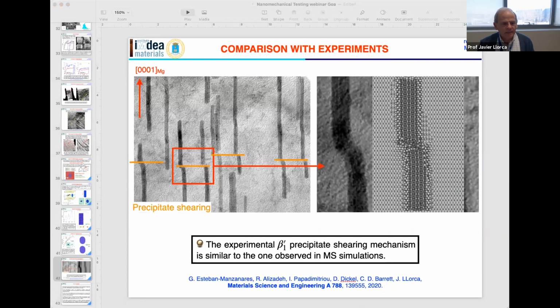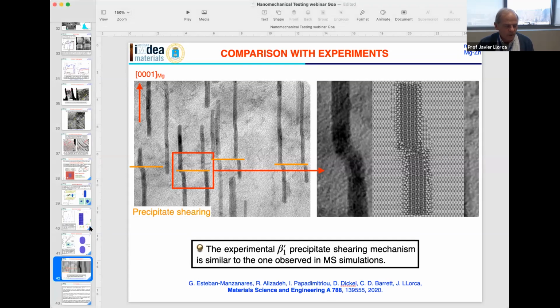This is just the precipitates after being sheared by dislocations. You can see here very clearly how the precipitates have been sheared. This is a high resolution TEM picture. So you can see here how one precipitate is about to be sheared, and another precipitate has been sheared. And these are the results of the molecular dynamic simulations. And you can see here the formation of the kink. So it's very clear that these molecular dynamic simulations show very clearly what is the shearing mechanism, which is similar to the experimental one. So this confirms why we have shearing of the precipitates and the reduction in the critical resolved shear stress.